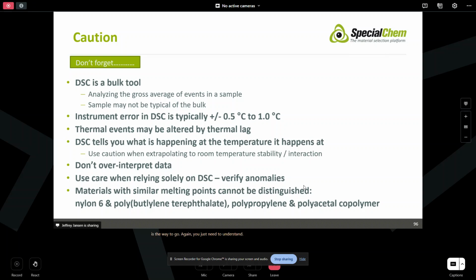Instrument error in terms of measuring temperature can be plus or minus 0.5 up to 1 degree. Our instrument's a little lower than that, probably closer to 0.1 degrees C. But again, understand your instrument and what your thermal reproducibility is. Might not be a bad idea to run the same sample a few times so you understand that. Thermal events can be altered by a thermal lag. DSC tells you what is happening at the temperature it happens at.